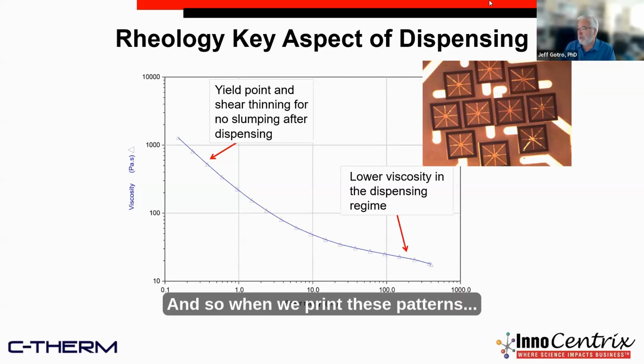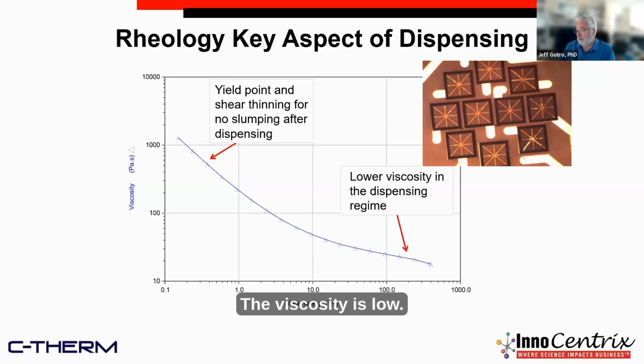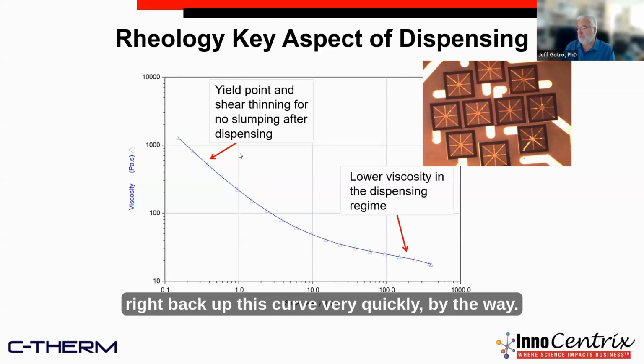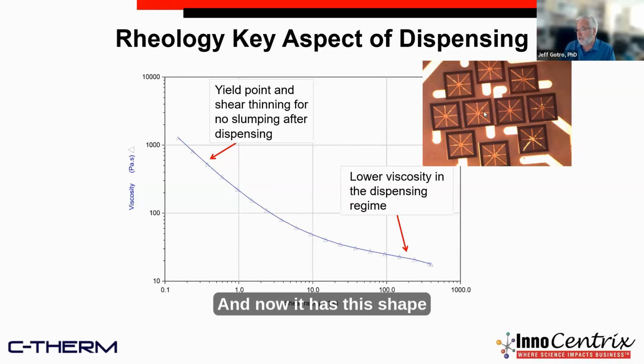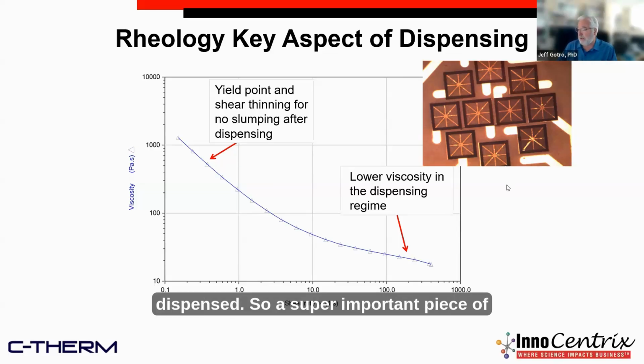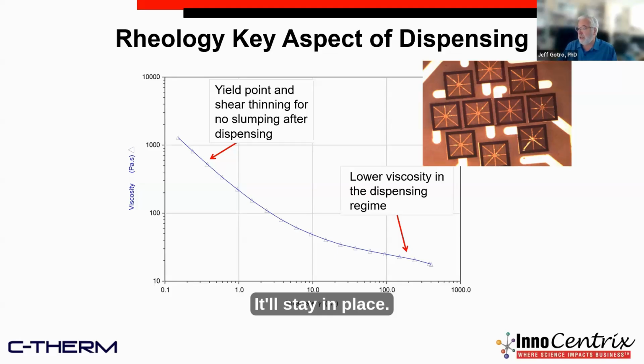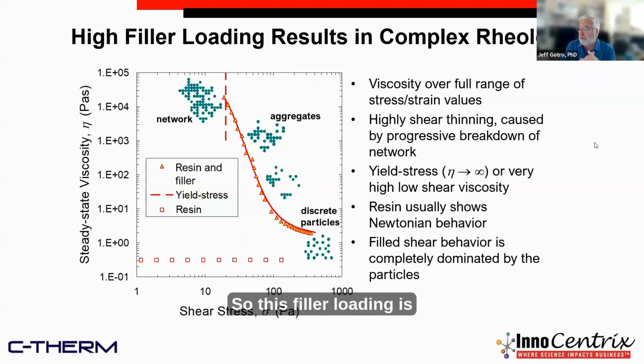This is an example of a die-attach adhesive, this picture up in the right corner, where we've printed what we call a snowflake pattern. When we print these patterns, we dispense at a very high shear rate, on the order of 300, 400, 500 reciprocal seconds. The viscosity is low, so we can print the snowflake pattern. But then when we stop dispensing, the viscosity goes right back up this curve very quickly, by the way, and now it has this shape that it maintains after it's dispensed. A super important piece of the rheology is that we can put the adhesive where we want it, and it's not going to run and dribble out all over the place. It'll stay in place.